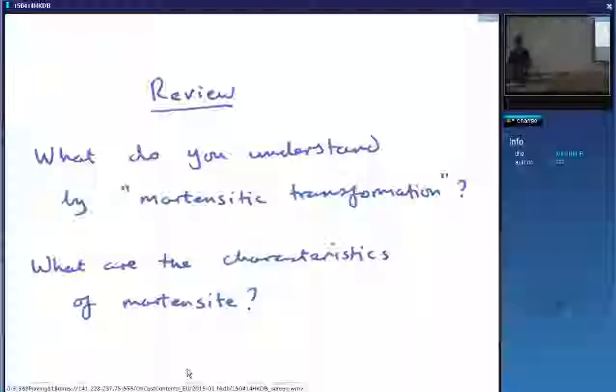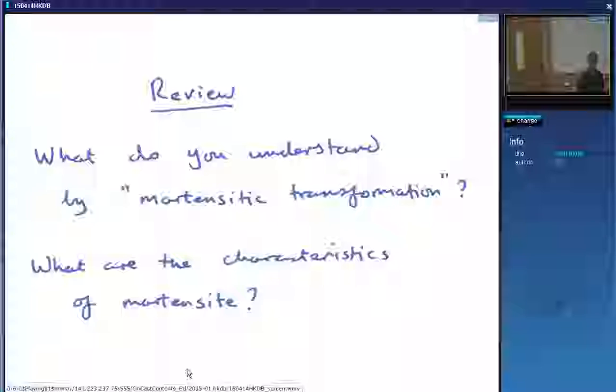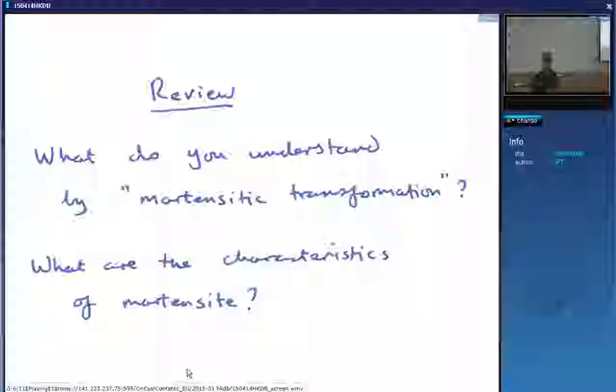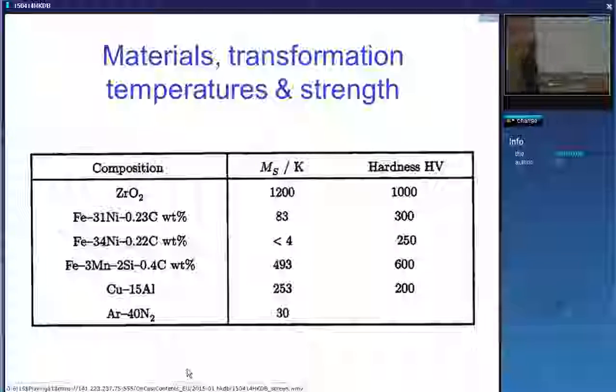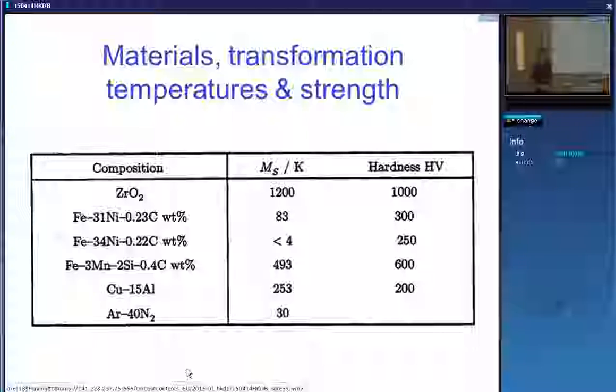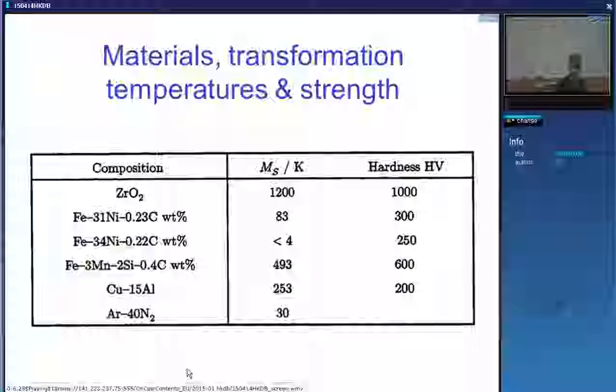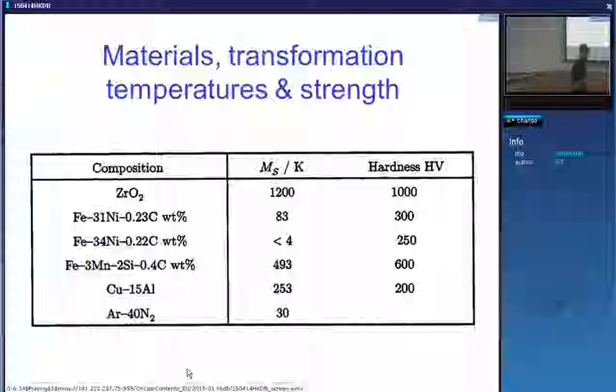By the end of today's lecture I'm going to leave several questions open, so it will seem that we have accurate but confusing experimental data. In the next lecture, you'll see a beautiful theory which solves everything. The first thing to note is that martensite does not have to be hard — it can be very soft, in which case it's not brittle. It's the presence of carbon that makes it very hard. Now why does carbon make martensite hard but not austenite hard?